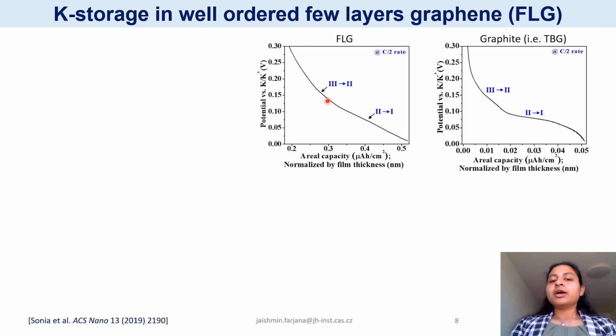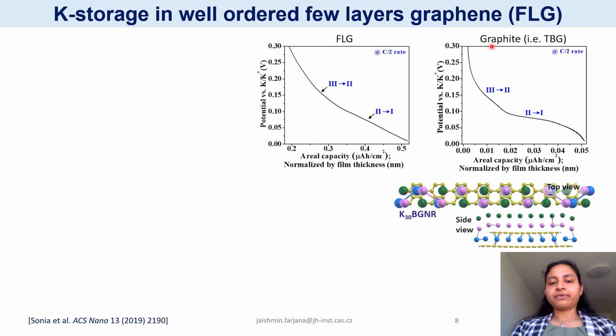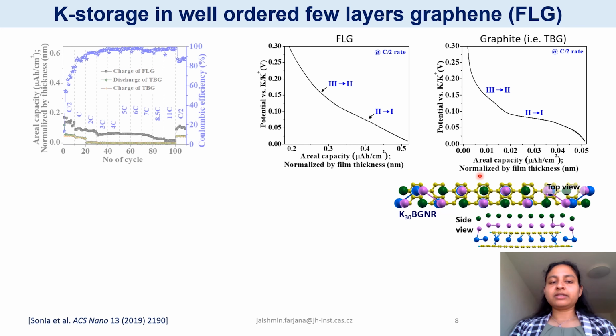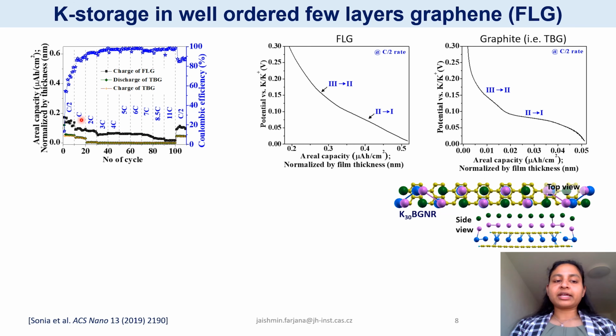And this phenomenon gives rise to the higher capacity in this few-layer graphene. We also studied the potassium storage in this well-ordered few-layer graphene, and we observed a similar potential plateau for few-layer graphene and the graphite. So its storage mechanism is quite similar to that of lithium, with a higher capacity for the few-layer graphene when compared with the bulk graphite.